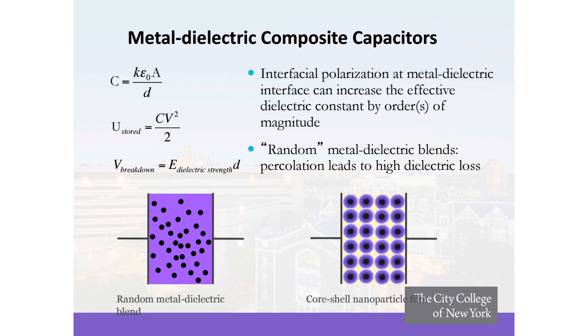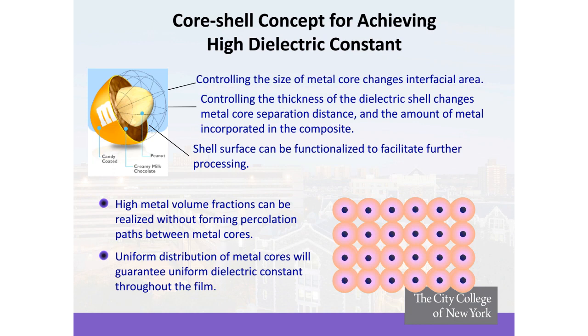And because the dielectric shell prevents the actual percolation between the metal cores, we end up with materials that have very high dielectric constant. So one can think of these cases where we are building, in essence, peanut M&Ms, the peanut being our metal core, the chocolate being our dielectric material, and the color of the actual candy is the surface modification that we functionalize each particle with. The ability to functionalize each particle allows us a very straightforward way of arraying these particles onto a substrate using interfacial electrostatic interactions.